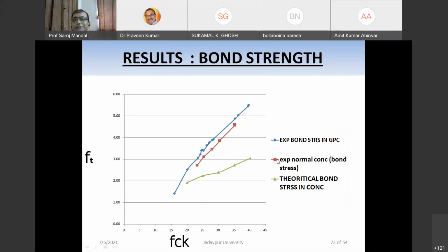So if you see the results of this bond test, that is your fck and the ft is the bond values, and this blue color is the experimental values of bond strength. Experimental normal concrete bond strength, that is, we use the same grade of concrete. Then comes the theoretical bond stress in concrete, right? How the theoretical bond stress is given as per the IS code. That is, if you know the fck grade of concrete, correspondingly we can calculate this.